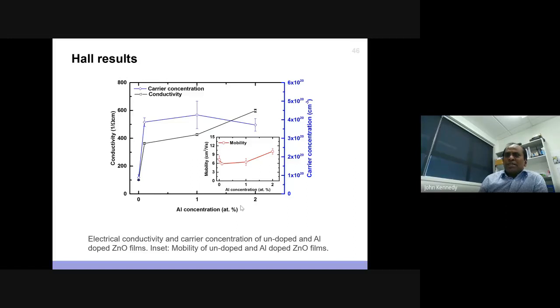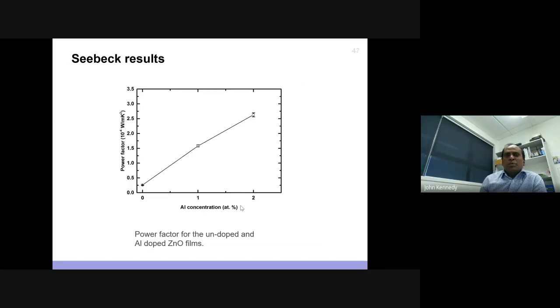So let's get into the real one, conductivity. What happens when you have aluminum zinc oxide? Can you really tune the conductivity? You can see that we are able to change the conductivity by having 1 or 2% aluminum concentration, and the carrier concentration is reasonably stable. The mobility is changed slightly as well. So this means you can change the conductivity nicely, and we are maintaining the increase in conductivity. The reason is the increase in carrier concentration and electron mobility. So when you go to Seebeck and the electrical conductivity together as a power factor, we are able to increase it as well.